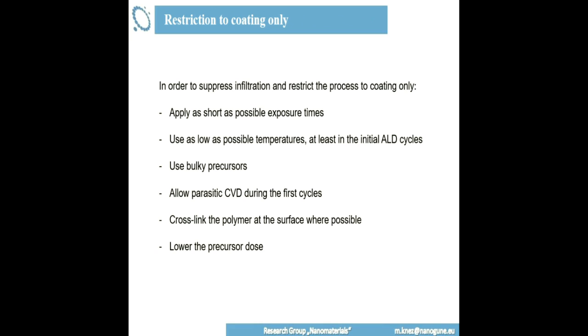You can also allow a parasitic CVD in the initial stage, just to block the polymer surface. And in this case, the next ALD processing steps will only see an inorganic surface. That means you coat and you prevent the precursors from seeing the polymer, with just a little bit of CVD at the very, very beginning. You can try to cross-link the polymer on the surface chemically with organics to just lower the capability of uptaking precursor molecules. And you can, of course, also lower the precursor dose, because then you have effects on the osmotic pressure outside and inside of the polymer. Several ways. You can develop more if you want. I didn't have any further in mind at this point, so therefore there is some space here.